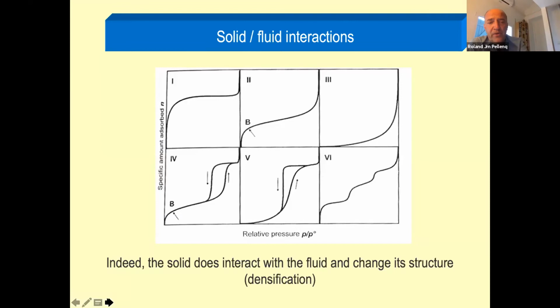So on the way up, we don't take the same path. On the way up, when we increase the pressure, we suddenly have the building up of this film at the B point and so on, and suddenly the pore fills up totally with liquid. When we depressurize, we try to take out the fluid, but the process doesn't go through the same path, and we have this hysteretic behavior that is fully connected to the fact that we have a first order transition of the fluid inside the pore system.